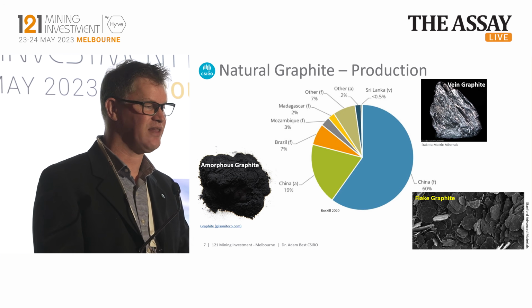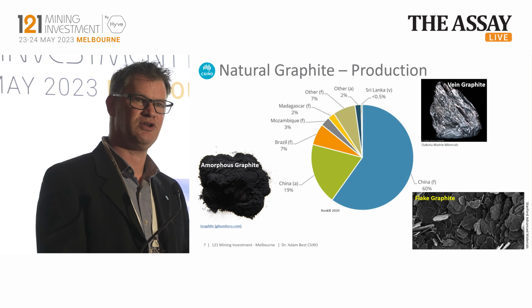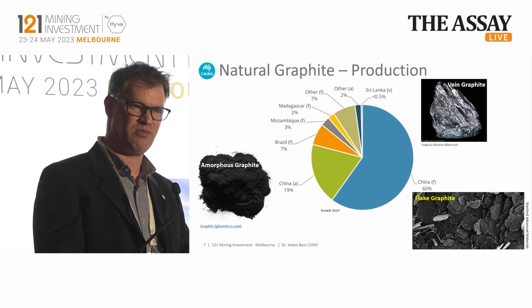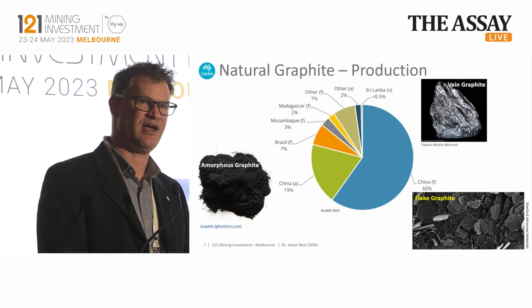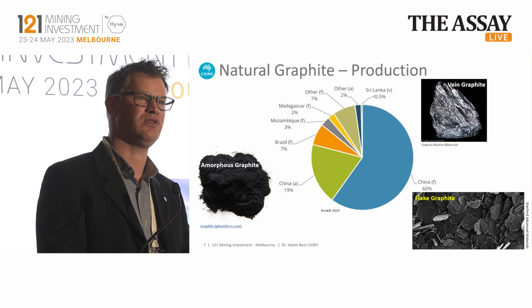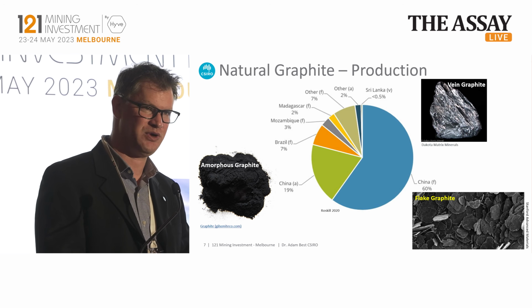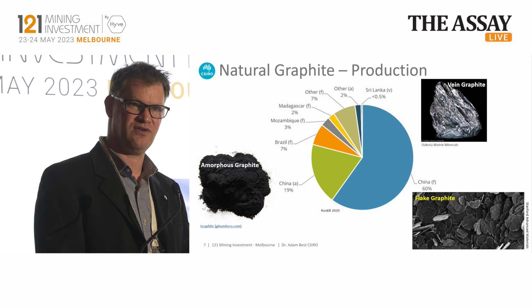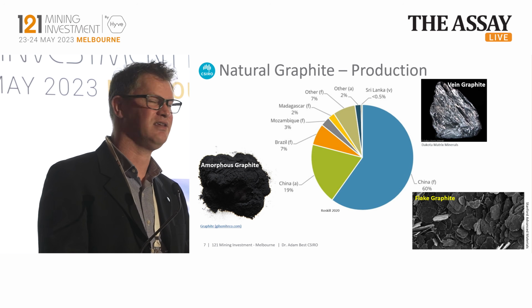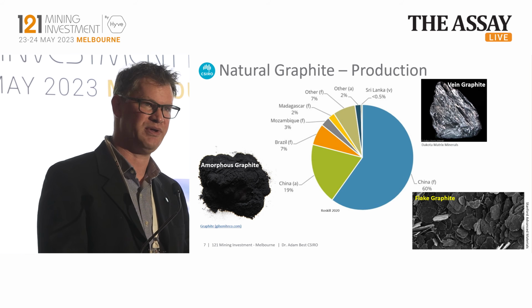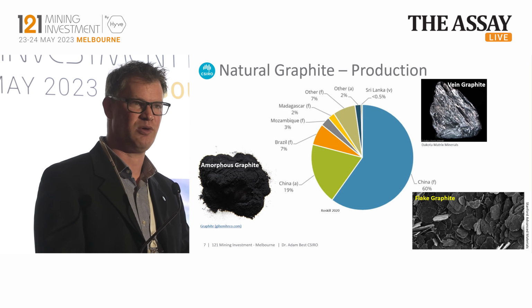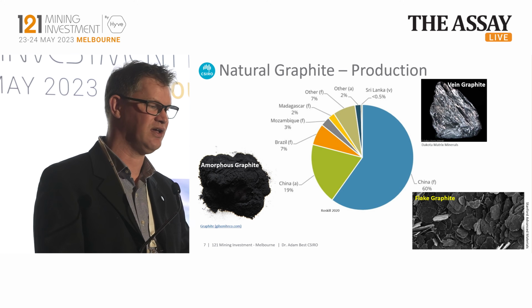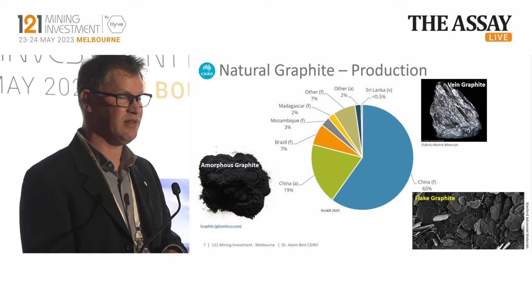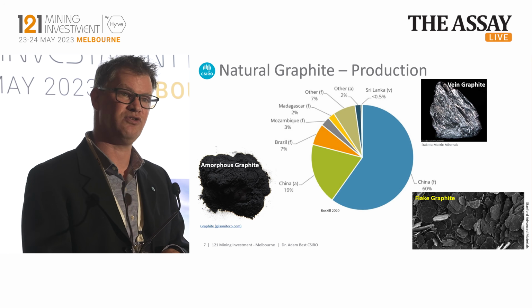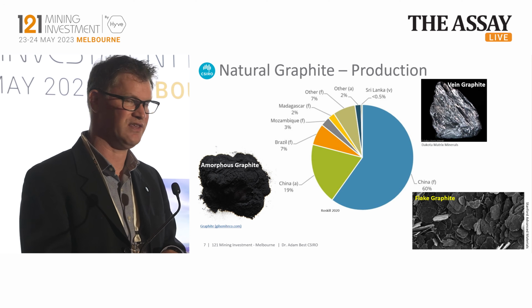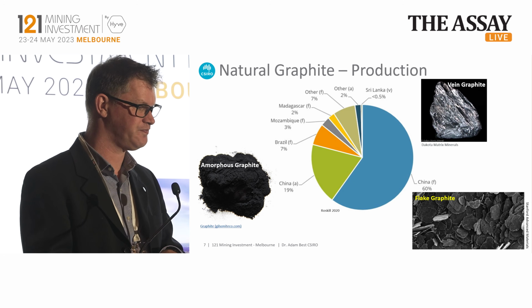So one of the interesting things about this field is that depending on your mine, you'll have different types of graphite. So a mine site in Queensland and a mine site in Western Australia will not have the same grade of graphite, will not have the same flake size, will not have the same impurity matrix. Similarly, if I get a graphite flake from Mozambique or Tanzania, yet again, it'll have very different geological properties, and so we will need to understand those properties in order to be able to successfully recover that graphite from the source. And depending on the size of the flake of graphite, we may need to do additional processing before we actually try and turn this material into a battery anode.